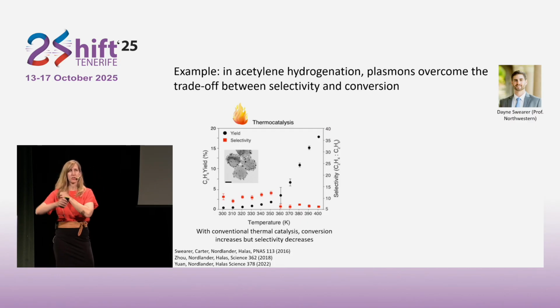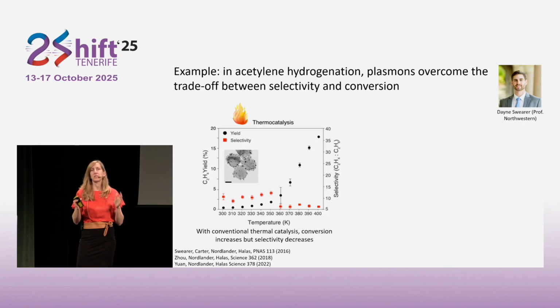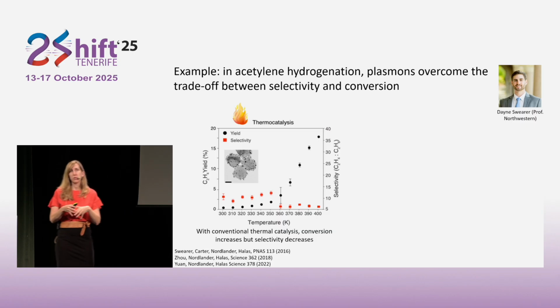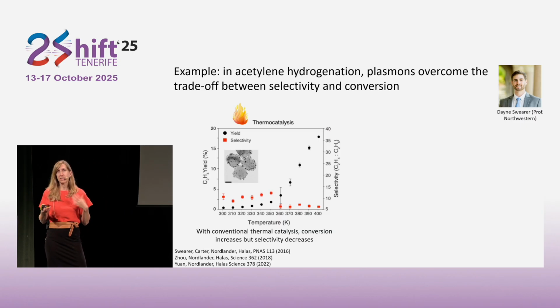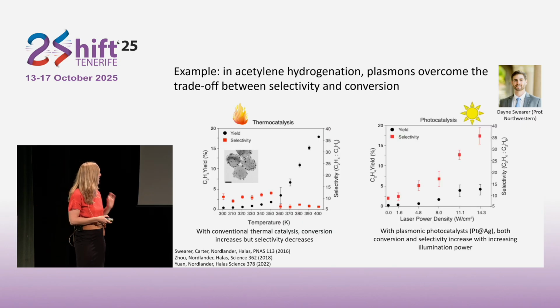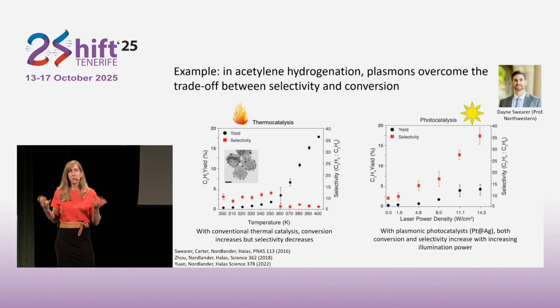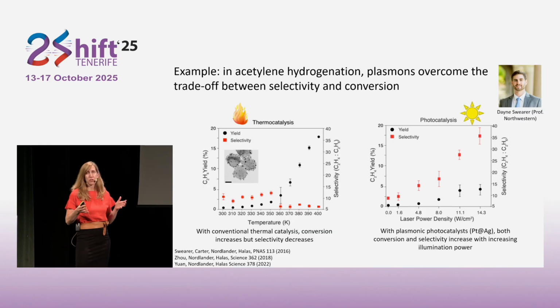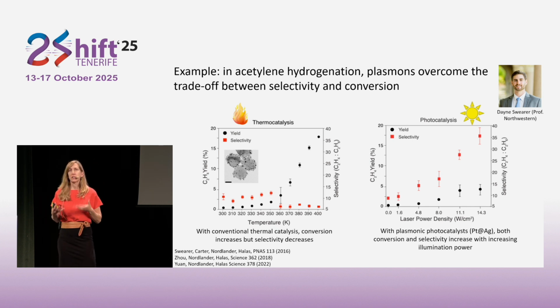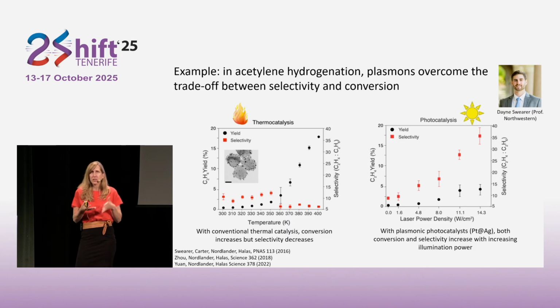So as you increase temperature, you can get more product, so your yield goes up, but you actually get less of the product you want. The selectivity for creating ethylene, as opposed to other products that sometimes can be poisons to the downstream catalyst, there's a trade-off there between yield and selectivity. But interestingly, he found that when he illuminated his reactor bed, that trade-off went away. Both the yield and the selectivity kept going up as he turned up the laser power. So this is showing that it's not just by illuminating that you're controlling the local temperature. There's actually something more going on.